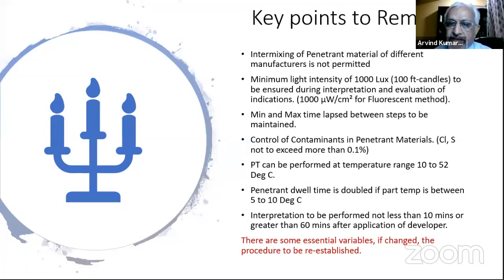So these things people do miss out, like a procedure made in Mumbai, and the job is being done in, it has happened with me, I have seen that in Chenab, somewhere near Kashmir, and the same procedure is being followed, where in the winter the temperatures sometimes go even below 5 degrees. So it's not that you cannot do it, you can, provided you follow the correct steps. Because the viscosity of the penetrant becomes high, and it will take more time to penetrate. That is why you have to allow extra time.